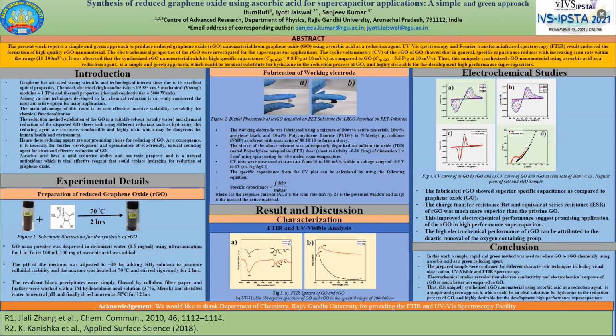This work presents a simple and green approach to produce reduced graphene oxide and studies its electrochemical properties. The preparation technique was quite simple: the dispersed solution was ultrasonicated and stirred at 70 degrees Celsius for 2 hours. The prepared sample was confirmed using FTIR and UV-visible spectroscopy. To study the electrochemical behavior, the sample was coated on a flexible substrate using spin coating. Cyclic voltammetry concluded that reduced graphene oxide has high specific capacitance as compared to pristine graphene.